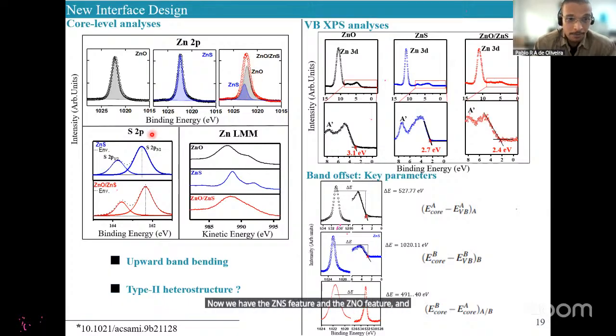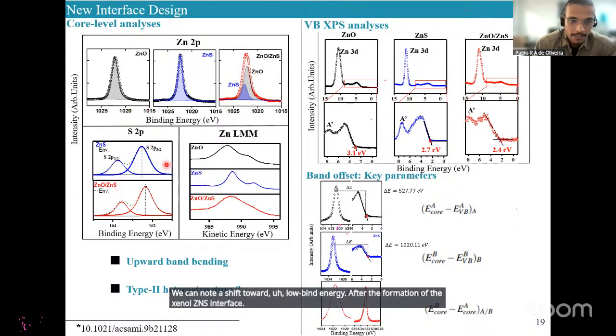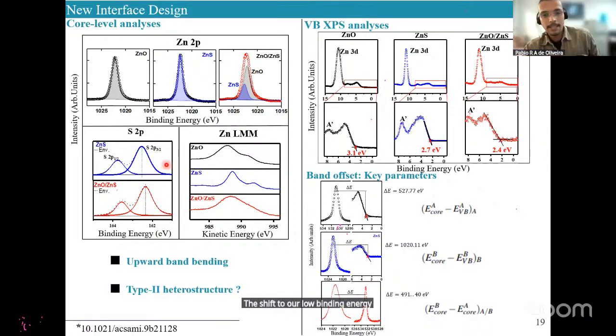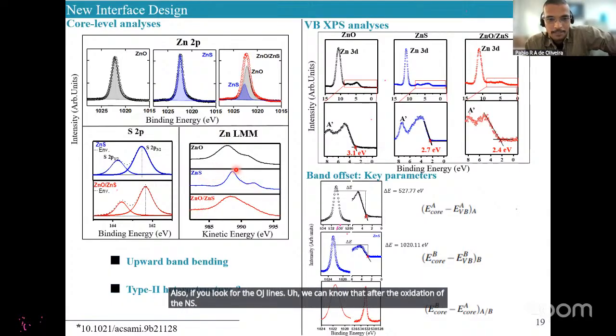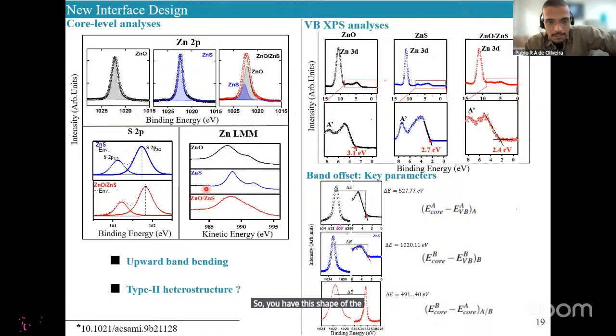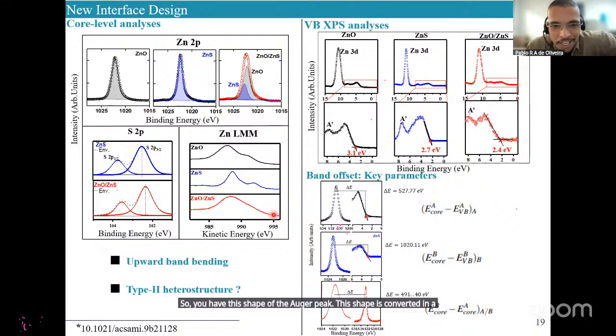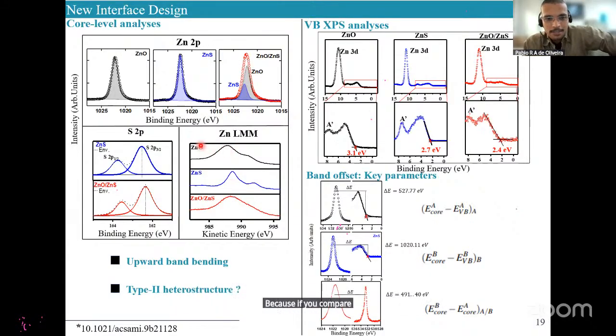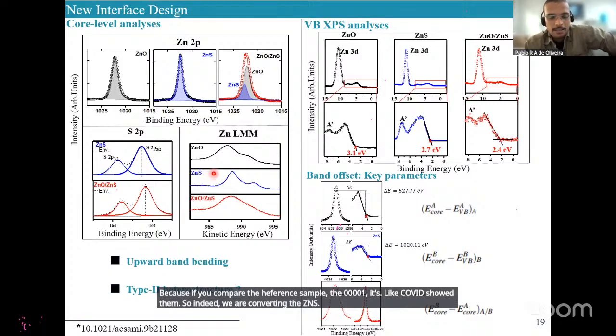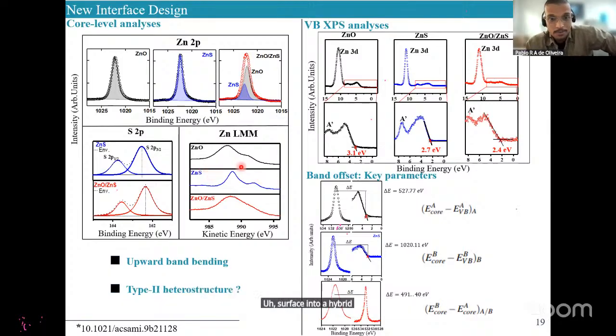Interestingly, if you know the sulfur behavior, we can note a shift toward low binding energy after the formation of the ZnO-ZnS interface. The shift toward low binding energy always suggests a band-bending-like effect, which might take place during the introduction of oxygen into the lattice. Also, if you look at the O KLL lines, we can note that after the oxidation of ZnS, this shape is converted into a ZnO-like shape, because if you compare it with the reference sample, ZnO 0001, they are quite close to each other. So indeed, we are converting the ZnS surface into a hybrid ZnO-ZnS interface.